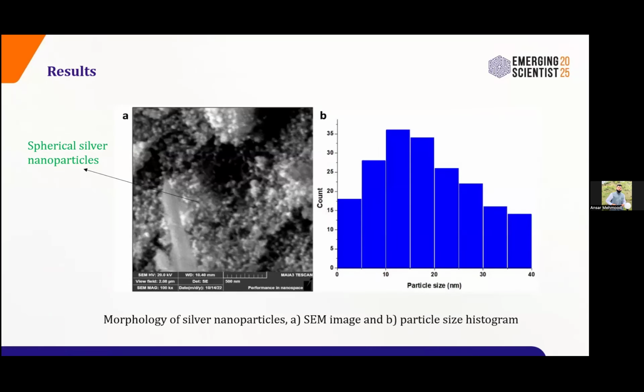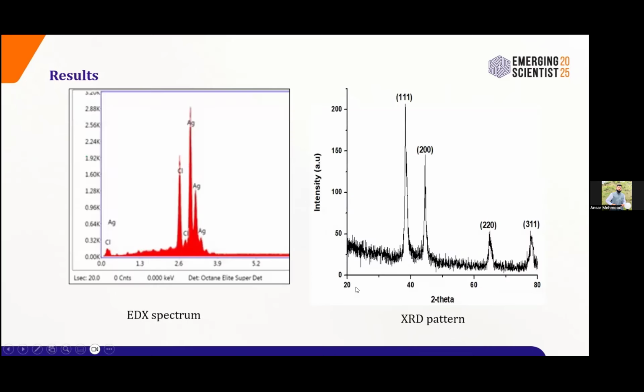And then here is the SEM figure of the nanoparticles, and here we can also see the spherical silver nanoparticles with an average particle size of about 18 nanometer. And the EDX spectrum clearly showed the presence of silver in the material, and the XRD pattern revealed the crystalline structure of nanoparticles.